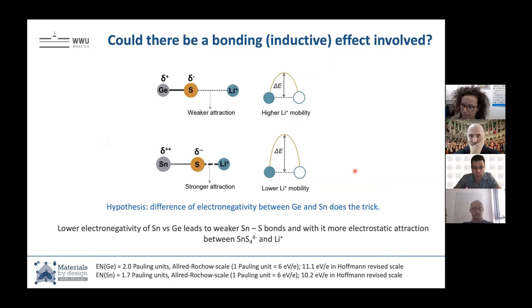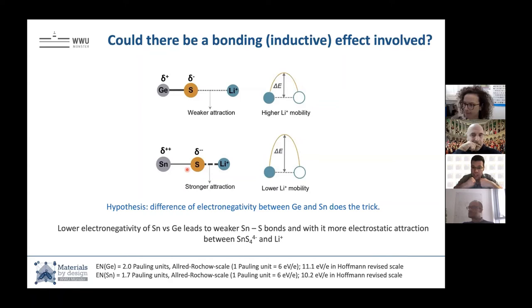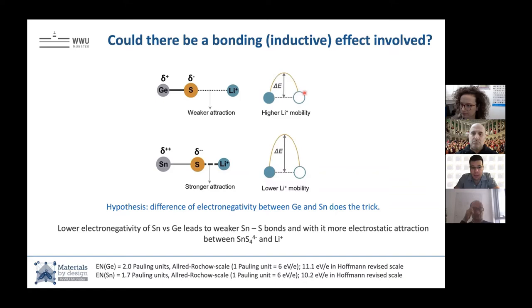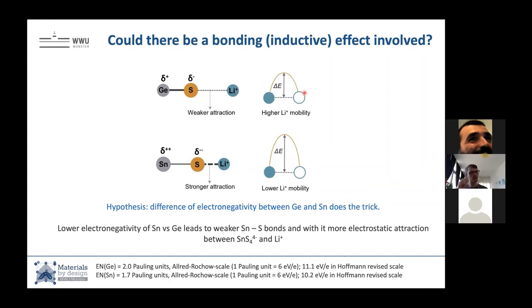Back then we put forward the idea that there's a difference in electronegativity between germanium and tin. Germanium is a little more electronegative than tin, so germanium in its covalent bond pulls more electron density away from the sulfur. Tin, being larger with a longer bond, is less pulling, so there is more negative electron density sitting on the sulfur. This higher electron density on the sulfur should mean a stronger Coulombic attraction to lithium, whereas in the germanium case there's a weaker attraction — and weaker attraction should lead to a lower activation barrier. This was our hypothesis, but hypotheses are one thing; we needed to prove it.